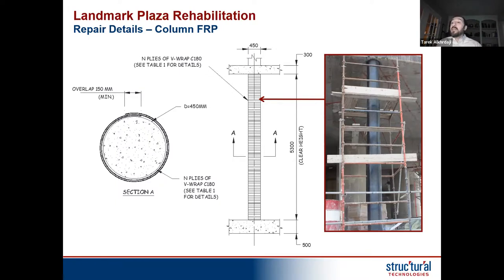And because of that, that column, we could not do it with FRP, and we ended up enlarging it with a concrete jacket because we needed to increase the stiffness and the strength, which was not doable with FRP. So my point here, finally, is FRP is a good solution, but it's not a magic solution for all the cases. There are many cases in which FRP may not be viable.